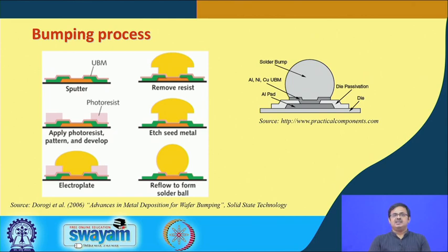All right. So, what is therefore done is, this structure with the gold or the solder is then made to reflow, and it forms a solder ball, which is typically spherical in structure. The reason this is done is, you reflow it in an oven, so that it just melts for a certain period of time, and then because of minimization of surface energy, it takes the shape of a sphere, thus forming this solder ball or the solder bump.